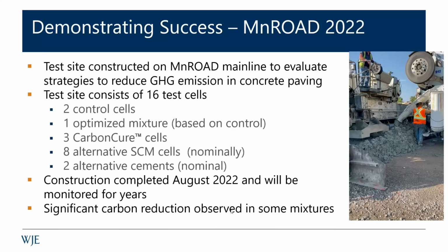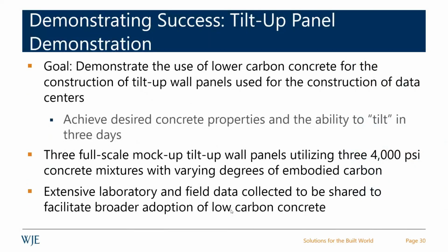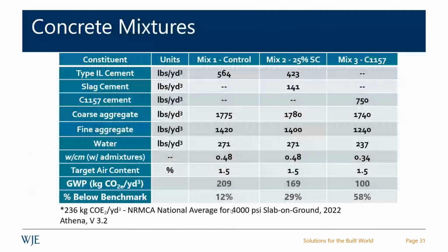States participate in that activity through what's called the National Road Research Alliance, and a lot of great work has come out of MnROAD. We've demonstrated low carbon tilt-up construction, where we went out and used these mixes. I want to just show these to point out the carbon reduction. Even our control mix had a 12% reduction off the NRMCA national average benchmark, but a mix with 25% slag cement was at 29%.